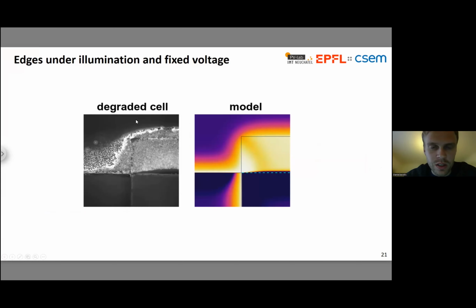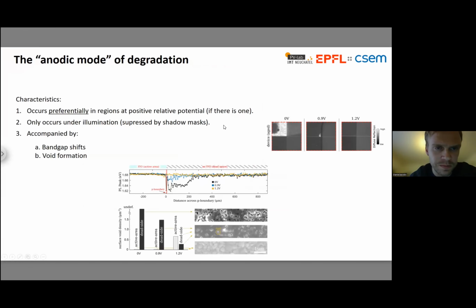So I showed this as my table of contents figure. On the left, a little zoom of this corner region where you have these very intriguing patterns of degradation, including these fronts that are coming off at an angle around the ITO boundary. The models with mobile cations do a reasonably good job of reproducing this. Some of these features are absent in the models with mobile anions. So I'm tempted to think that it's a mobile cation that's responsible for this damage, but the evidence is not completely in on that. It's a tentative indication.